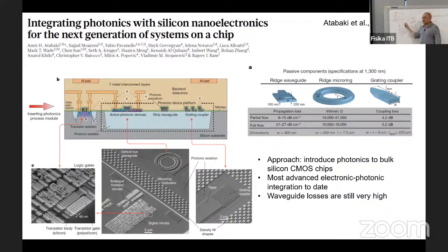So that means that if you have this kind of waveguide amplifier, the source light that you have at 1550 nanometer doesn't have to be too strong, right? But of course, this has been done in spiral waveguide where there is no nonlinear optics. But then what they did, and I know this because it's a former PhD student of mine that did this in a Science paper earlier this year, is that they have a ring that has nonlinear effect. So they pump it with a single frequency and they create multiple frequencies, a frequency comb, and then they couple this into this spiral, let's say, that has been doped by erbium to amplify all these lines, right? The next idea is, of course, to dope the resonator itself, like you said, to actually exhibit amplification. Does that answer your question?